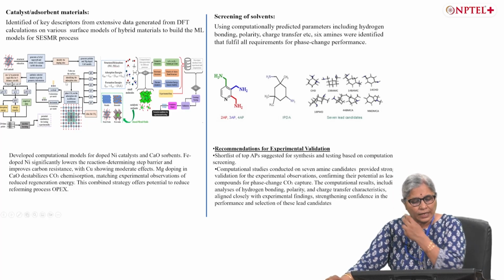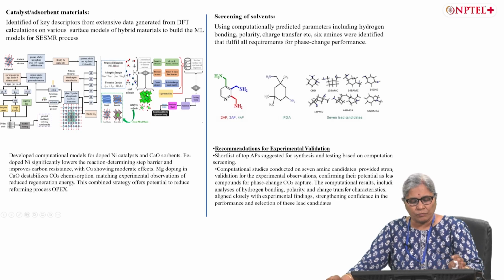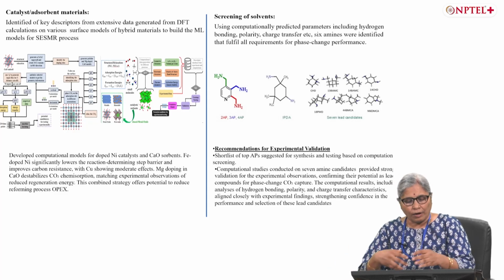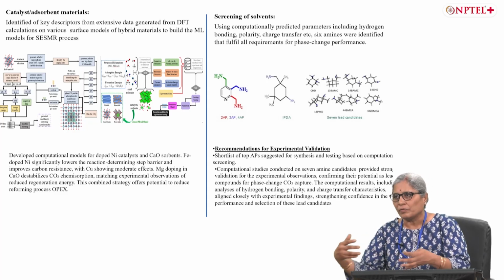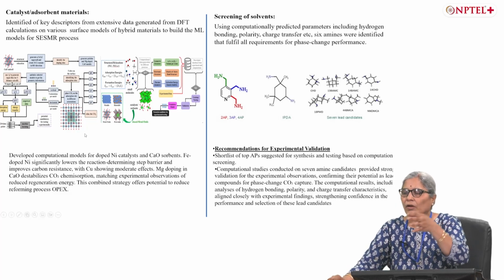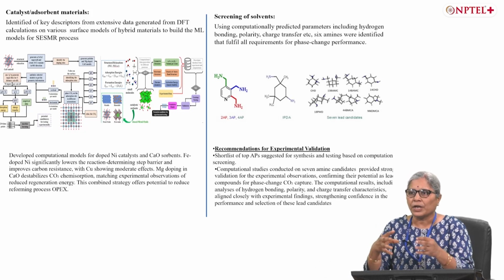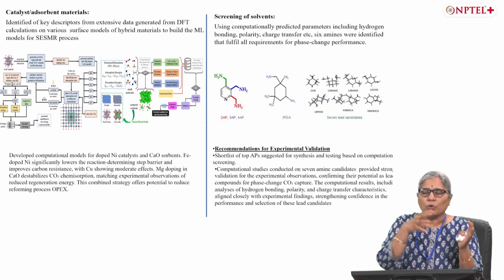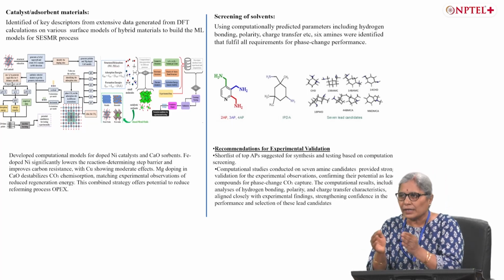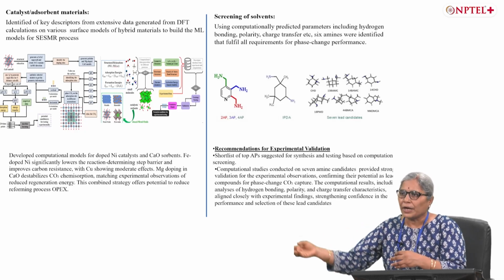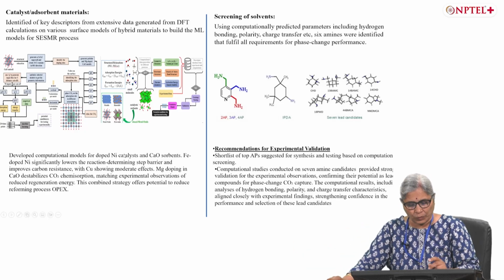For reforming of methane, we start with materials representative of a catalytic model, like a nickel cluster sitting on alumina, or iron, or any catalytic material doped with different transition metals, because for this reaction they use calcium oxide as the sorbent. So we combine in our computational model both the catalyst and the sorbent in a single particle, develop and optimize the model, and try to predict the properties for these conversions.